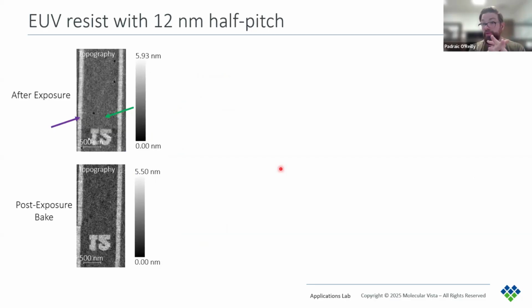Another application that PiFM has been used for extensively is investigating resists, with EUV latent imaging being the most prominent recently. This specific resist is under IP, so we will not show any spectra of which wave numbers were used. But we can go through the experiment and how it compared with other analytical measurements.